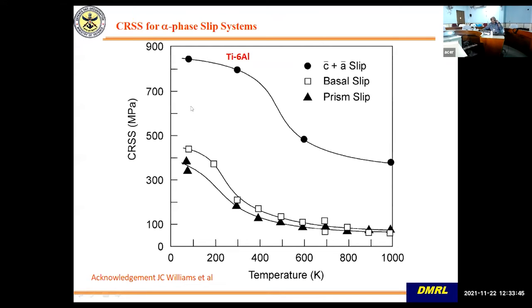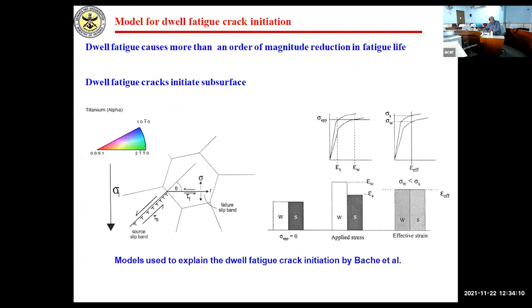Then the C plus A slip, as I had told you, there is a huge difference in stress requirement, C plus A slip or pyramidal slip. So this is much higher. The stress requirement to cause this kind of slip or deformation is much higher. Why am I talking about Ti6Al? Because this is the common unit in all high temperature titanium alloys. Okay. So that is why this is important.